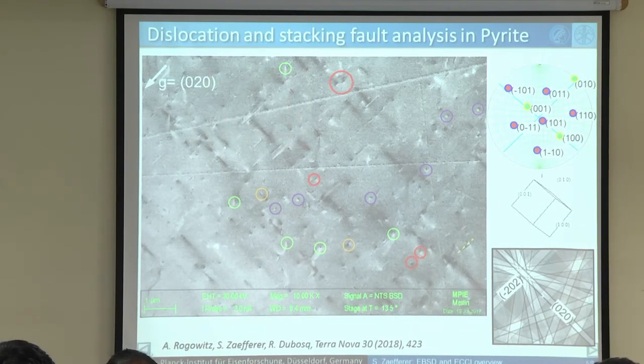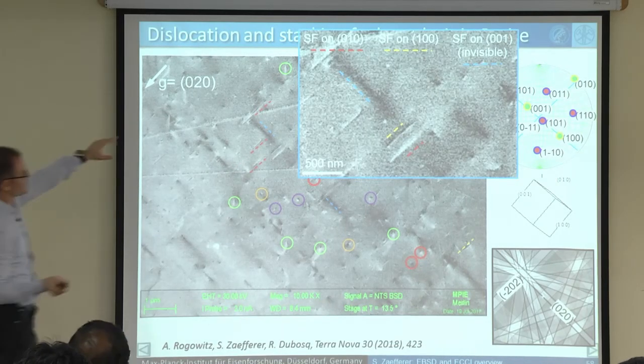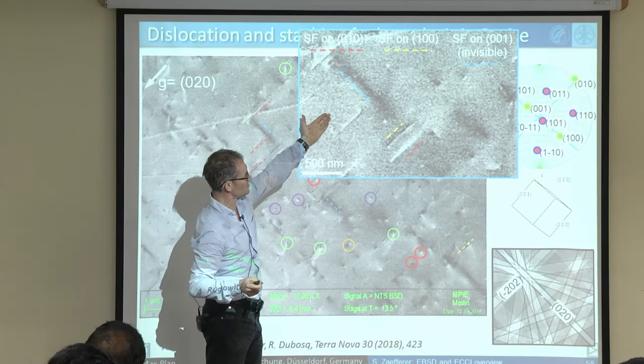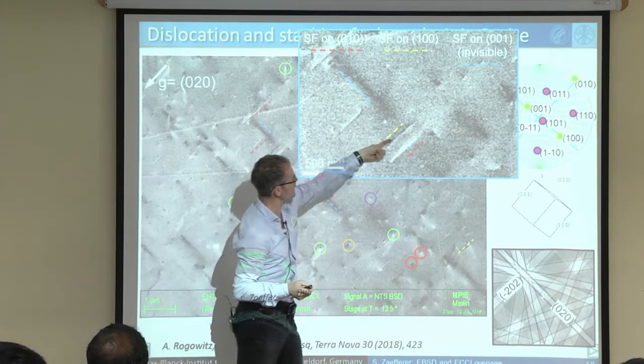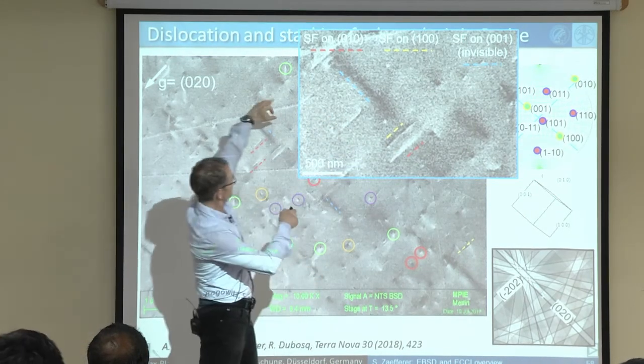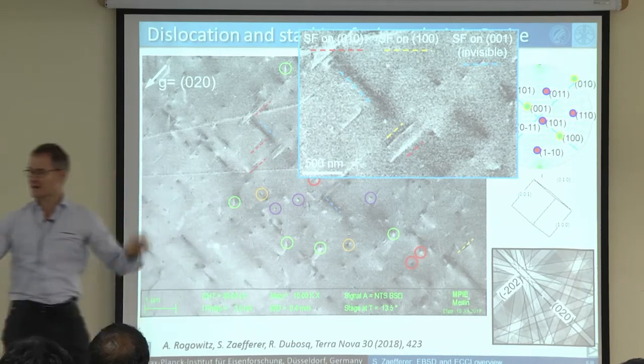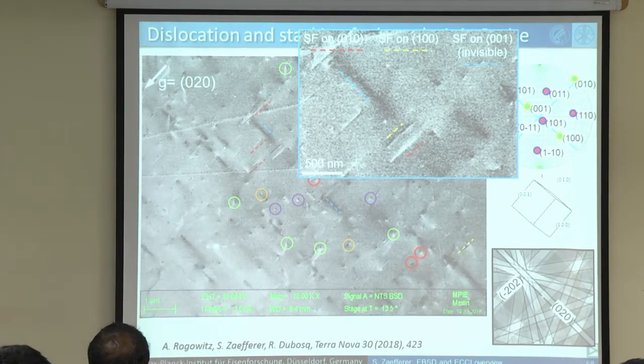And then we have all kinds of stacking faults. This yellow ones, blue ones, red ones, and they all have very typical differences in their contrast. One is white-black, one is black-white, one is white only, one is black only, and all of these we can analyze with crystallographic knowledge. We get it all out of that. So you see how powerful that is.